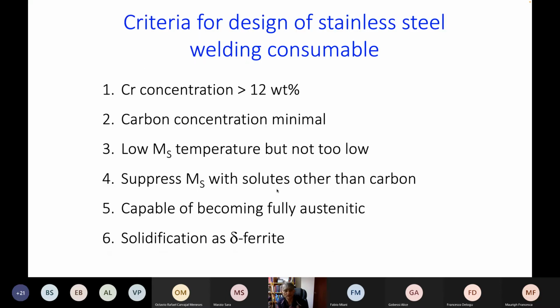Now, these are actually transformed into ferritic transformation products, but supposing we wanted to design a stainless steel containing a large chromium concentration, okay? So we need a chromium concentration greater than 12 weight%, because that gives you a reliable, coherent and adherent chromium oxide film on the surface, which regenerates if it is scratched. We must have virtually zero carbon concentration because of the problem of chromium carbides forming. We need a low martensite start temperature, but not too low, so that we can exploit the full capacity of the phase transformation. And we need to suppress the martensite start temperature with solutes other than carbon.